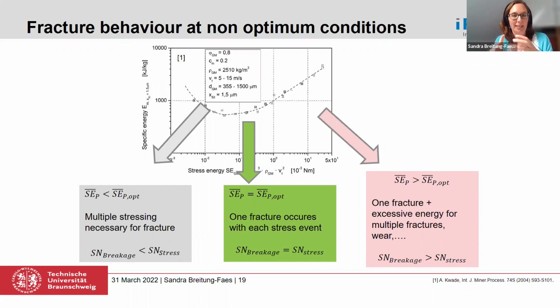And this has to be reflected somehow as well. But at least it's not going to be more efficient. Also, you have maybe more fracture pieces afterwards. You will also have a lot of excessive energy for wear, which is dissipated into heat. So here at the optimum stress energy, one fracture event should occur to one stress event to have two pieces afterwards. So this is the model idea behind this.